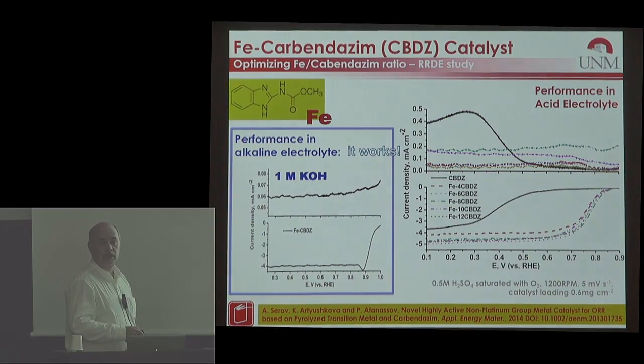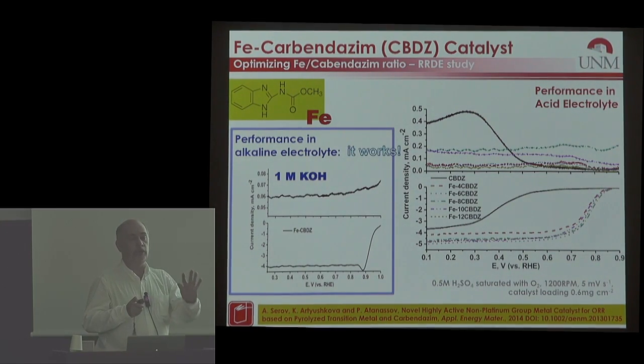And pyrolysis, I mean, the system is absolutely clean. We only have iron because we put iron in it. So if you pyrolyze these materials without any iron, you get a fantastic catalyst for hydrogen peroxide formation. It's like a textbook material. You can make peroxide with it and sell the peroxide if you want. And putting more and more nitrogen to the same amount of carbon makes the catalyst better and better. So this is the equivalent of what Frederic showed you of putting less and less iron. In our case, we simply are increasing the amount of carbon-nitrogen precursor, which is the same effect, okay?